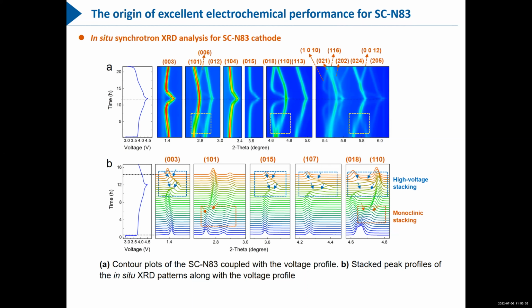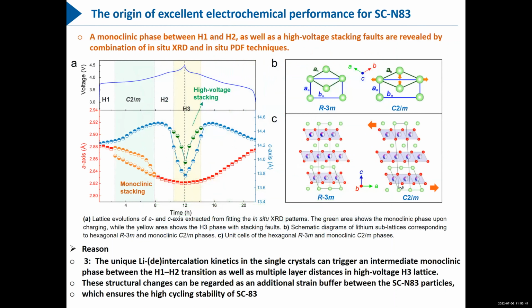We just try to dig out more structural information from the in situ XRD. This is the lattice parameter change for the single crystal materials. For a typical NCM material, normally the phase transition transforms directly from the H1 phase to the H2 phase and to the H3 phase, with no monoclinic phase. But for this material, we find a monoclinic stacking here, and even at high voltage, the high voltage stacking is very complicated. This is very interesting.